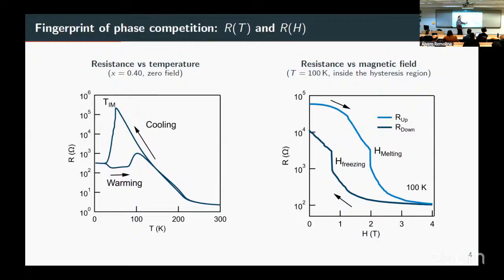So here I'm plotting the same resistance, but now as a function of magnetic field. If we are at some temperature, let's say 100 Kelvin, we have some particular value of resistance, but if you shift the magnetic field, then the resistance will go down by several orders of magnitude. And then if you decrease the magnetic field, you get the same effect, but you get to a lower resistance value. So many things we can discuss about these figures.